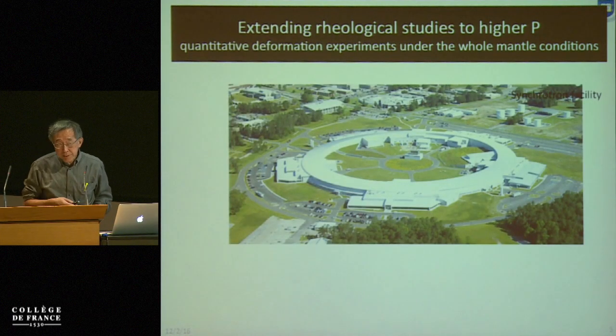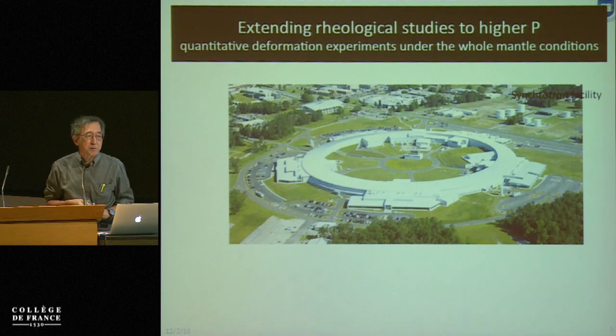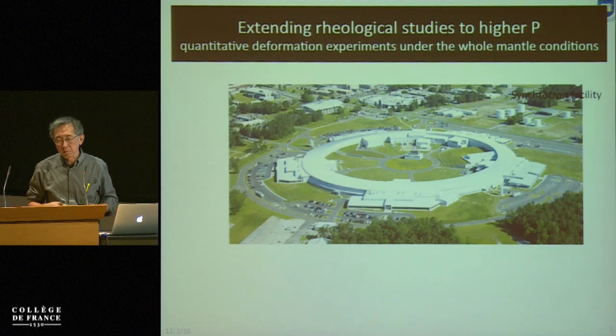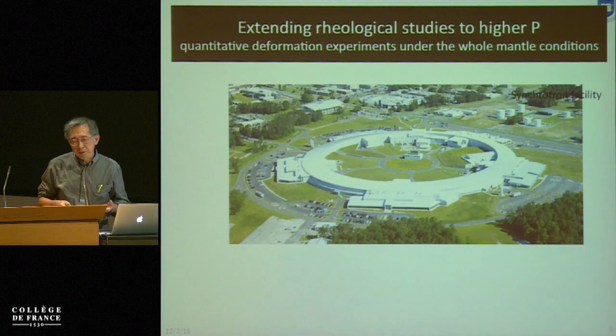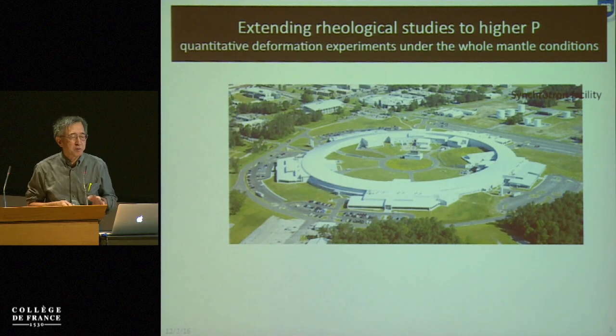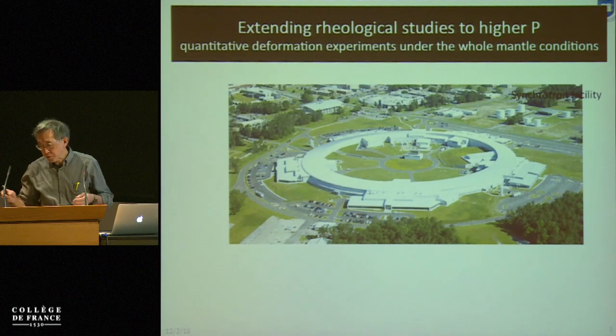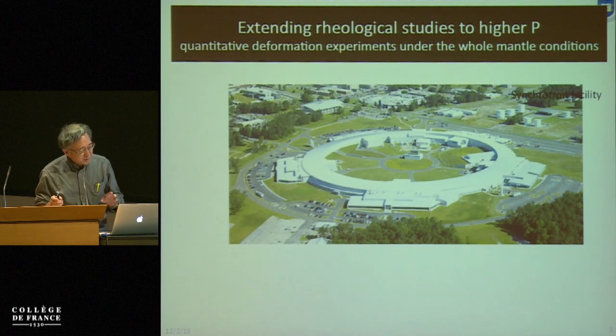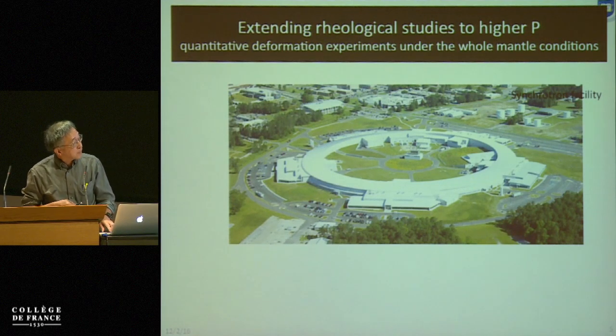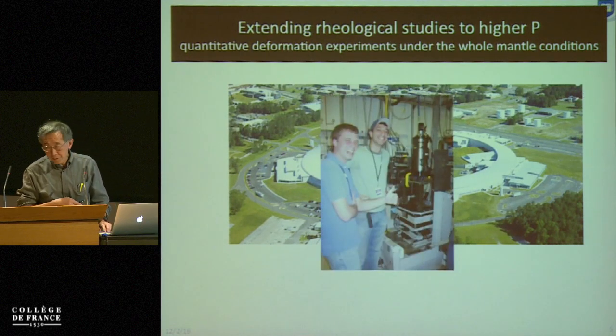To do experiments under those high pressure conditions, you cannot use conventional techniques like a load cell for measuring stress. You must use in situ X-ray technology, like a synchrotron radiation facility. In this case, particles are accelerated, and the particles emit X-rays. Very intense X-rays, and using X-rays, as I'm going to show you, you can determine stress and strain.